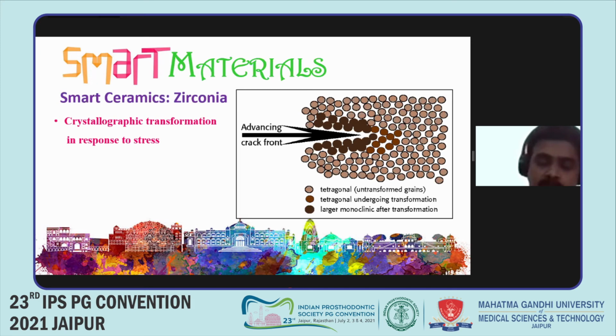Blessed is zirconia because it has a tendency that whenever it is subjected to stress, tetragonal form gets converted into monoclinic form. Now, how exactly is monoclinic beneficial for us? It is because monoclinic form has a tendency to occupy more space. To be very specific, 4.4% larger space, the crystals become larger in size, and therefore they themselves seal off the crack which is propagating.